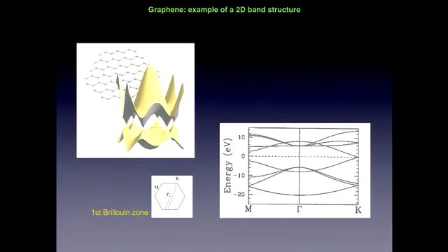Another way of saying that is that the density of states at the Fermi level in a metal should be non-zero. And here it, in fact, goes to 0. Although just above and just below the Fermi surface there are states, right at the Fermi surface it vanishes. So it's this marginal case between a metal and an insulator, and we call it a semi-metal. And it has some interesting transport and other properties that are reflected by this.